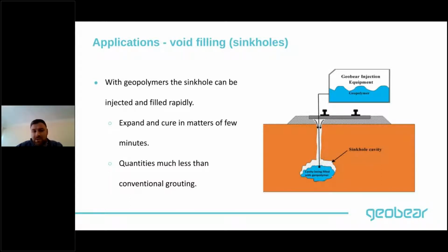The advantage of using this technique is that, first of all, it's going to expand and cure very quickly. It's not like if you fill it with grout, where you have to wait for a few days to get the full strength. With this, you'll get the full strength in a matter of a few hours at most, and then you can open your line back to traffic. The other advantage is that you're not going to be using as much quantity as you would have used in conventional grouting, because geopolymers can expand, and because of that, you can use much less quantity of material.